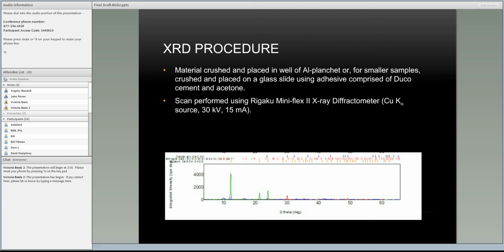And to go over the XRD procedures a little bit, you first have to grind down the sample and crush the soil. And you can do it 2 ways. We have this aluminum holder where you can put the crushed soil in that, or just use a small amount of soil and put it on a glass plate. And our system that we have is the Rigaku MiniFlex 2 X-ray diffractometer. And down here at the bottom is just an example of what a scan looks like.